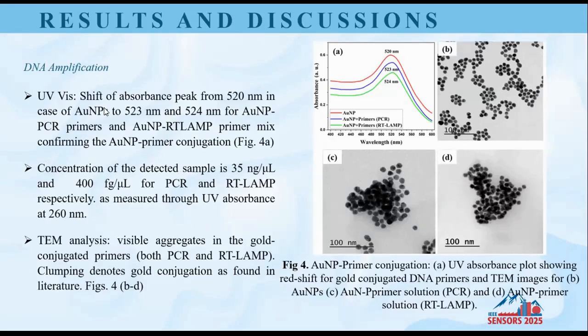So from the UV plot, it has been seen that the shift of absorbance peak from 520 nm to 523 and 524 nm for AuNP PCR primers and AuNP RT-LAMP primer mix confirms the AuNP primer conjugation. Secondly, during transmission electron microscopy analysis, we have seen clumps forming when we tested the conjugated solution. So the clumps indicate, or confirm, the conjugation process, as can also be supported by literature.